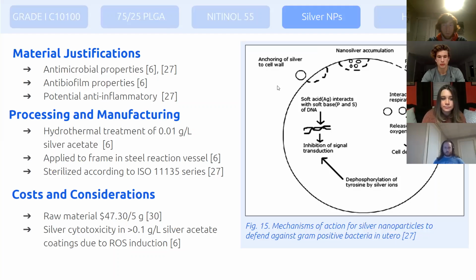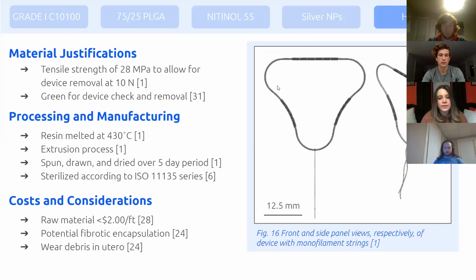Now, the high-density polyethylene monofilament strings adherent to ASTM D638 will be able to maintain tensile forces of up to 10 newtons for device check. Above 10 newtons, the device should be able to collapse and exit. They are designed to be checked every year during the patient's gynecology visit, and the neon green string color will contrast nicely to the native tissue, allowing for easier check and removal on the clinician end. The monofilament will be processed via extrusion methods to achieve a diameter of 0.25 millimeters. The polymer will be sterilized with ethylene oxide gas. Similar to the PLGA polymer, however, the polyethylene may provoke fibrotic encapsulation, but because this device is medically inserted using the patient's own anatomy, meaning no incisions are made, we are only anticipating a low to moderate inflammatory response for both of these polymers.